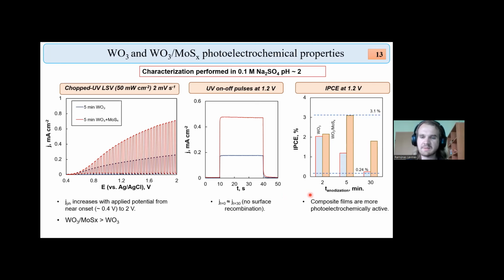And when comparing films that had been synthesized by anodization for different times, that is 2, 5, and 30 minutes, we noticed that the most effective film, which gives an incident photon conversion efficiency of 3.1%, is obtained as the composite film that had been synthesized for 5 minutes. However, another result that we notice is that the relative difference between the tungsten oxide and the composite is much larger when the film had been synthesized after anodization for 30 minutes. So the composite does have more effect, not on thin, but on thick films.